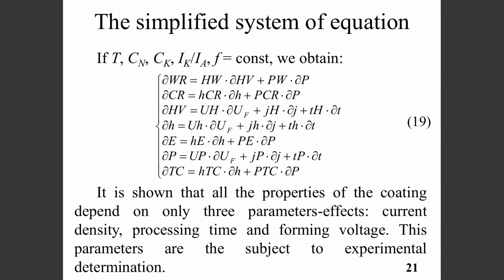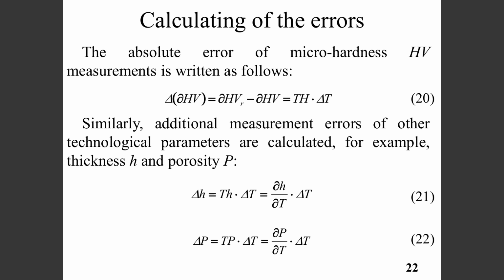Taking into account the fact that some technological parameters are sought to be stabilized in production, the system 18 can be simplified. The analysis of the system 19 showed that all parameters reactions characterizing the properties of the coating depend only on three parameters effects: current density, processing time, and forming voltage. Within the framework of the graph model, expressions for calculating methodological errors in determining the properties of coatings, arising from the instability of technological parameters, for example electrolyte temperature, presented on the slide, were obtained.